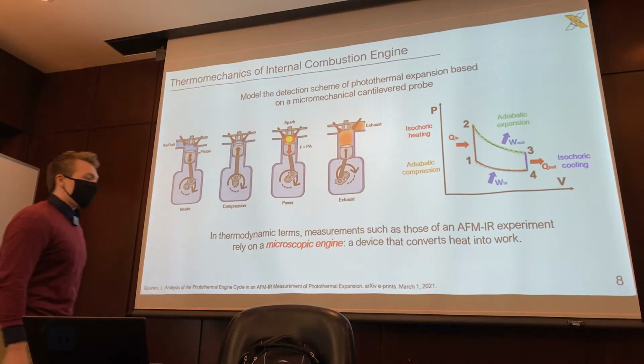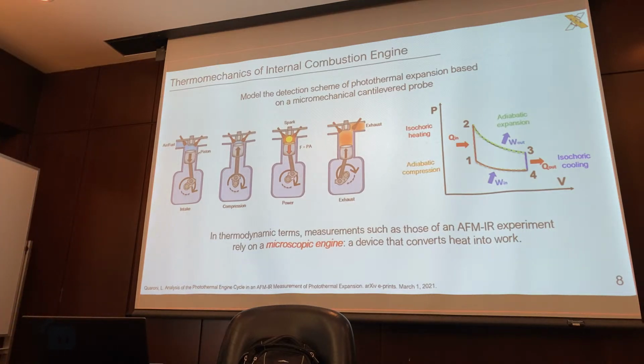And so we can visualize this in a PV diagram, as you can see on the right-hand side, where you receive energy between process 1 and 2, where we experience max pressure during the compression period. Now, we get an adiabatic expansion when we move from point 2 to point 3, where we get work out, and this is this process here as we're moving the piston downward. From process 3 to 4, we're getting energy out, in the form of exhaust, and then we're putting energy back into it, and this process completely reverses, going from point 4 back up to point 1, moving to a point where we've reached minimum volume once again.